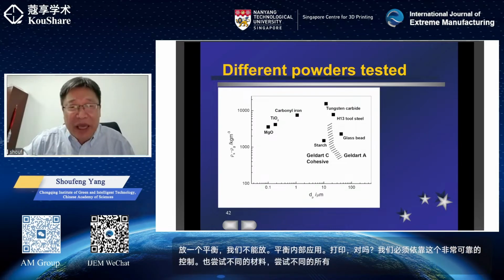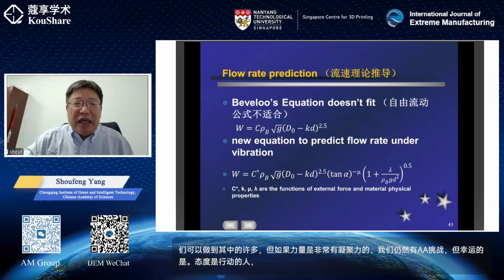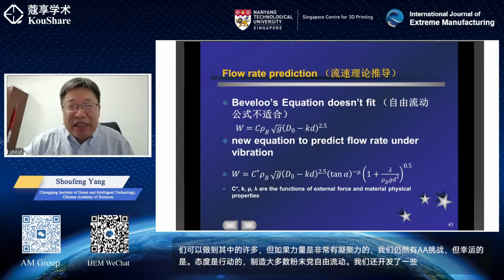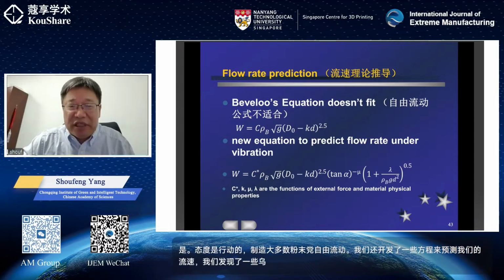We have to rely on this very reliable control, and also try different materials, try all different powders to see, can we do that? And luckily we can do many of them, but if the powder is very cohesive, we still have a challenge. But luckily for additive manufacturing, most powders are quite free-flowing. And we also developed some equations to predict that flow rate, and we found some Beverloo equation doesn't fit for such small scale, and we modified that.